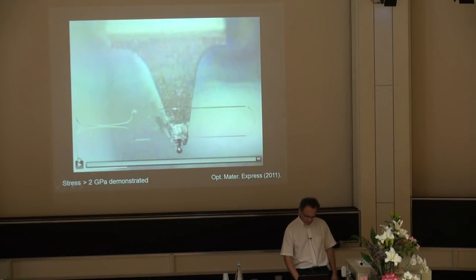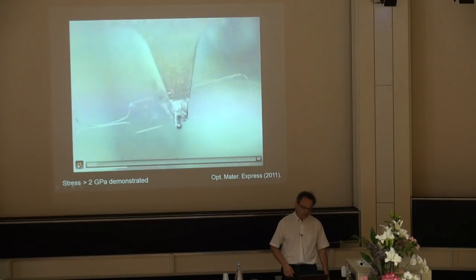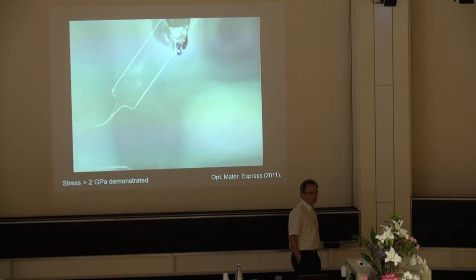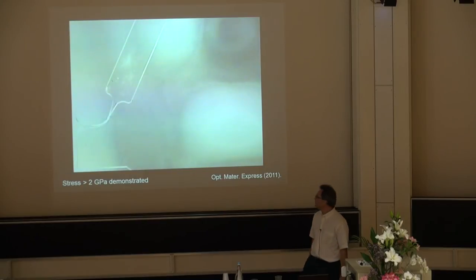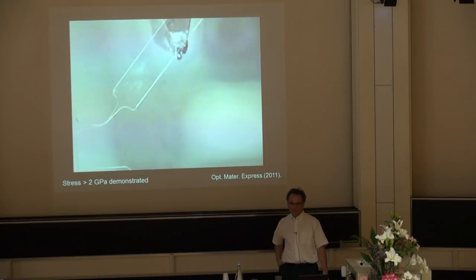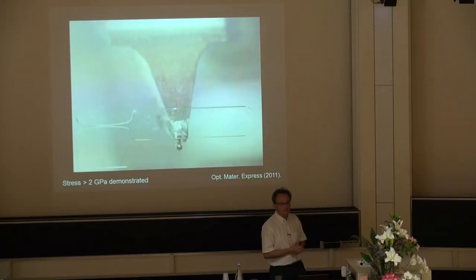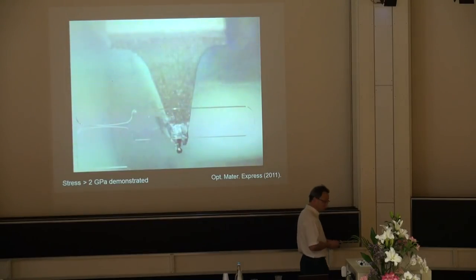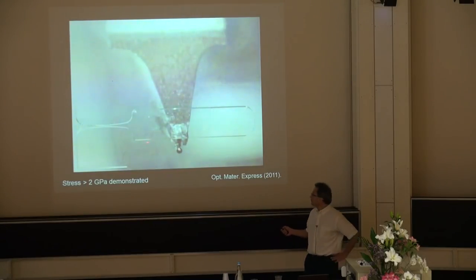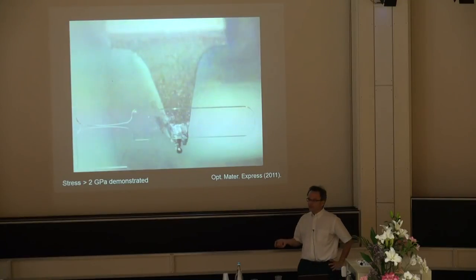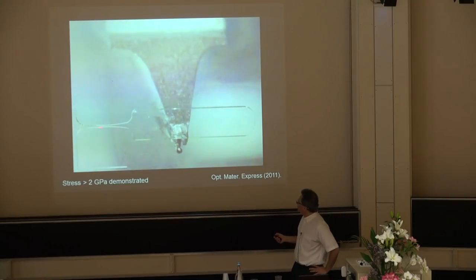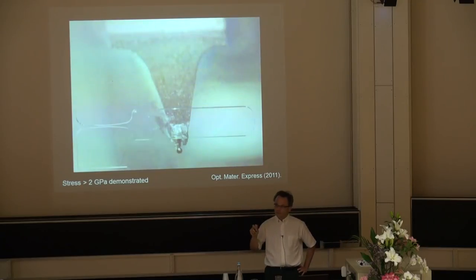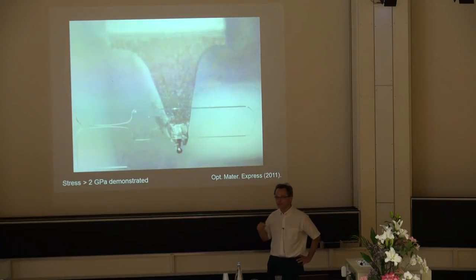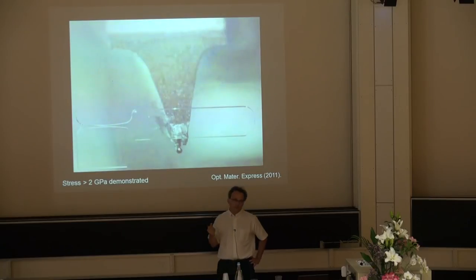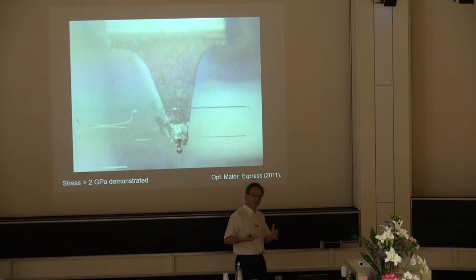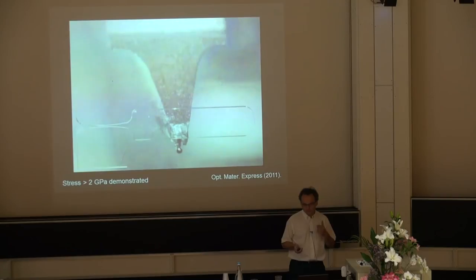In fact, nobody has ever really measured the elastic limit of glass, because it's driven by the surface effect. What drives the ultimate limit of when it will break is mostly the surface. So if I have some defects, then it will break instantly. But here, let's not forget, first of all, the laser is very confined, so the modifications are extremely localized. The second aspect is that we do a chemical etching, so in a way we clean up the surface of any defects that might be there.